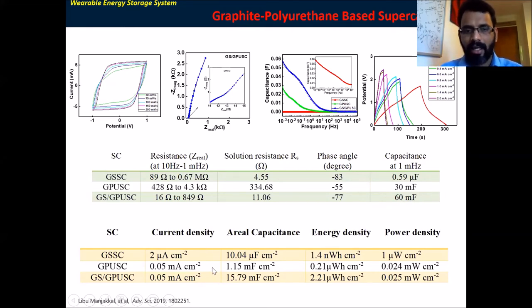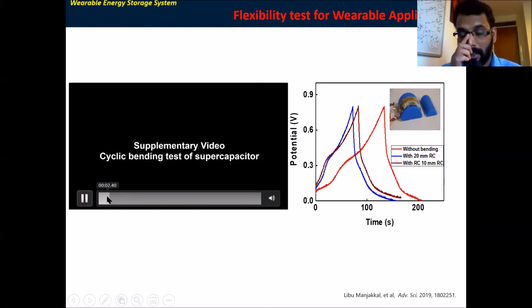And then in energy density at a fixed voltage of 1.1 volt, you can see that the device shows 2.21 microwatt hour per centimeter square. But in the case of a device with 2.2 volt, I observed almost 10 microwatt hour per centimeter square for the energy density of this device.